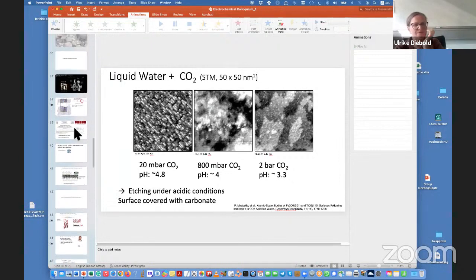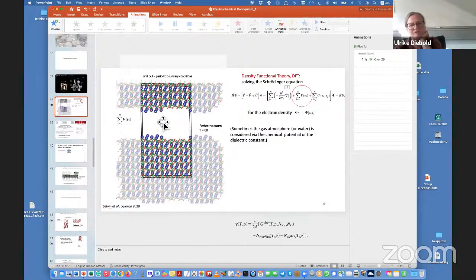In real life, what will happen is, actually in this paper, we've looked at potassium tantalate, which is an intrinsically polar surface. And we looked at how polarity is alleviated when you cleave it. First it is electronic. Then if I go up in temperature just a little bit, things start to move. You'll form vacancies, oxygen vacancies, by just lateral motion. At some point, there will be a restructuring of the whole surface to alleviate the surface polarity. And if you put a little bit of water, then the whole surface will change again. So in the end, whenever you have a polar surface, the first thing the surface will do is automatically lower its surface energy by doing some sort of restructuring. That's my experience in this.